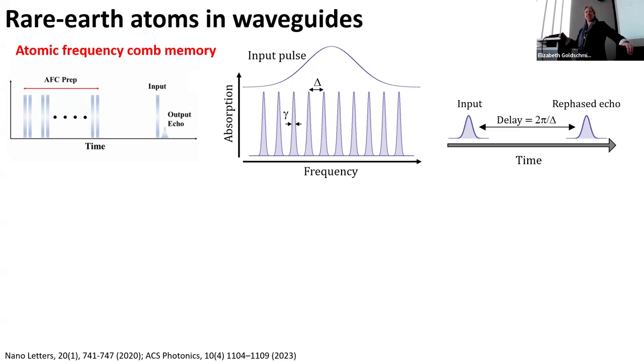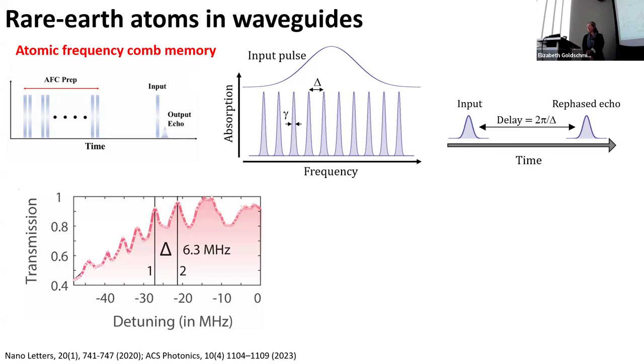Okay. One question. Is this slide for the next figure? Yeah, this one. It looks like you determine the delta between the two beams. Well, we choose the delta by controlling the pulse train that creates the comb. So the delta is in fact the inverse of the spacing in time between the pulses in our pulse train. In this figure, between the two peaks, it looks like it's not totally a comb? Well, that's because our comb isn't very good. For a variety of reasons, our comb was not very good, and so that's why it looks kind of nasty.